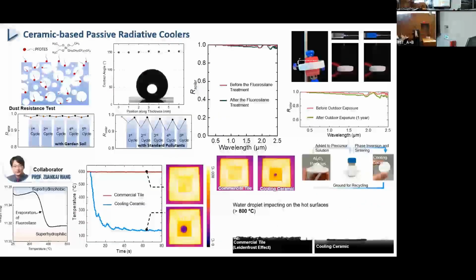In terms of dust resistance, we also performed tests outdoors to see if a lot of dust affects solar reflectivity. We found that when we do the self cleaning, the reflectivity recovers to around 90%. So dust will not cause failure.